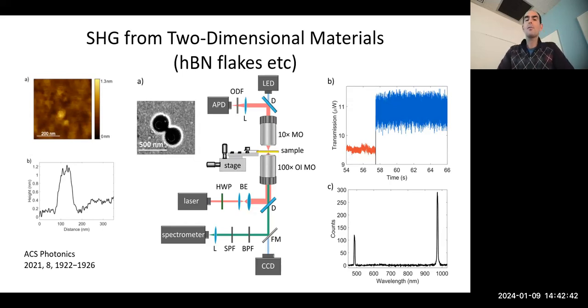So they give very large signal. But not only that, you see second harmonic generation. This might not be surprising to many of you who don't work in the field, but for people who work in nonlinear optics, to observe harmonic generation from a single nanocrystal with a CW, low peak power laser, is quite surprising. Usually people who do nonlinear optics use these intense, ultra-fast lasers, particularly for nano materials, relying on the huge peak power you get in a pulse laser, which gives a 1,000 or 10,000 times increase in instantaneous intensity to observe these harmonics, because the nonlinearities are typically so small.